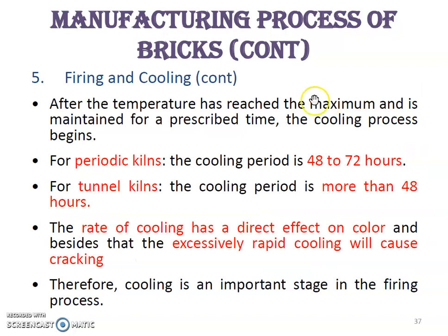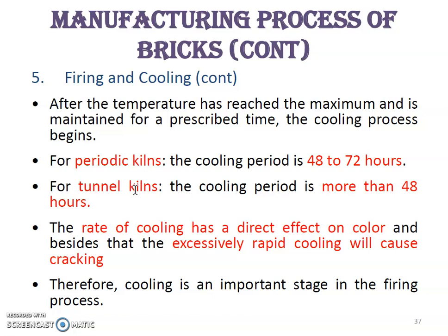After the temperature has reached its maximum and is maintained for a prescribed time, the cooling process begins. The cooling period for periodic kilns is 48 to 72 hours, while for tunnel kilns it must be more than 48 hours. The rate of cooling has a direct effect on colour, and excessively rapid cooling will cause cracking of the clay bricks. Therefore, cooling is an important stage in the firing process.